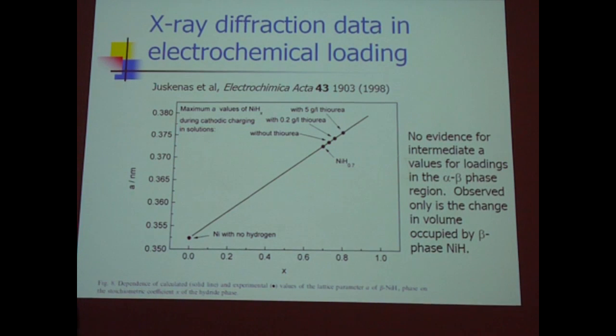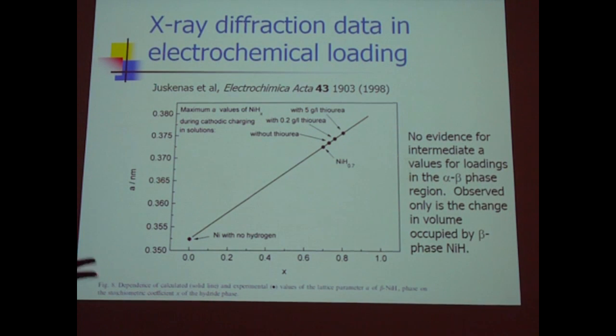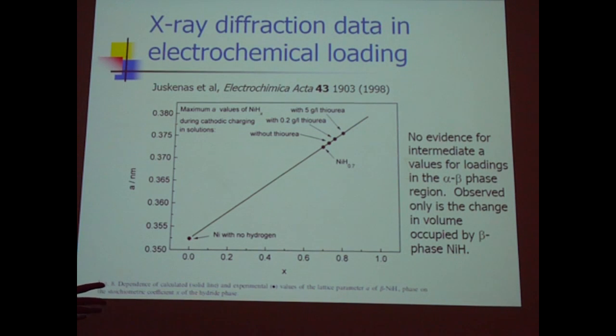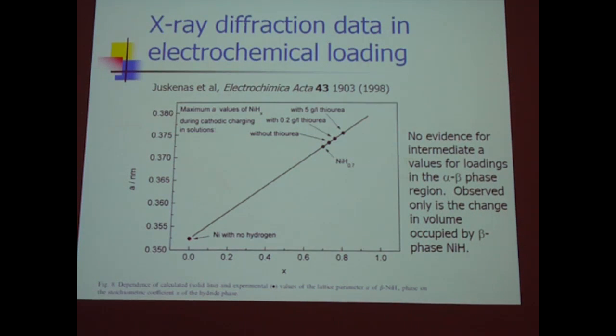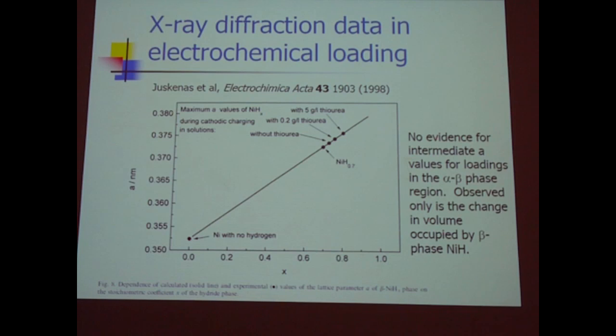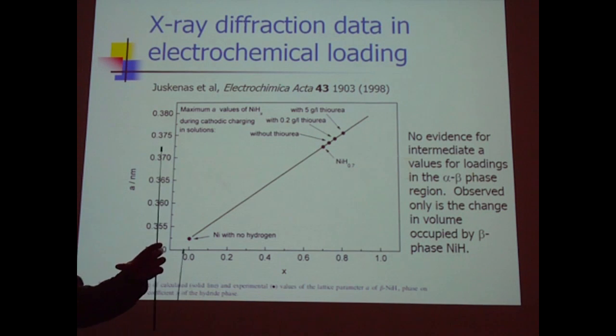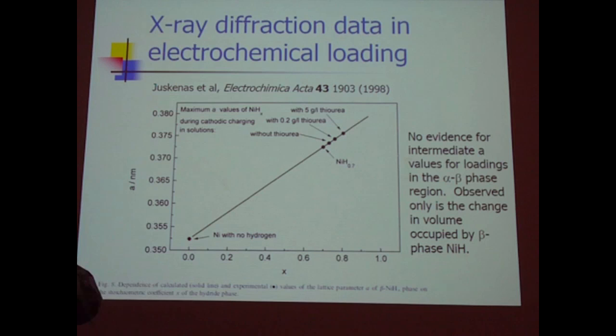Suppose you have nickel hydrogen loaded to 10%. You do your X-ray measurement. Most of the nickel looks like it has no hydrogen. Some of the nickel looks like it's loaded to 0.7. What's the answer? Clumping. The hydrogen likes each other in nickel, so it clumps together. You put in a little bit of hydrogen, it segregates. There's some here, there'll be a clump here, but mostly everywhere there's no hydrogen. You've just got bare nickel.